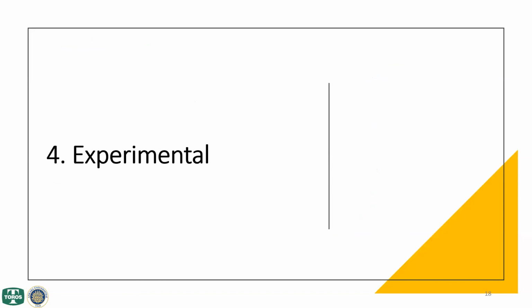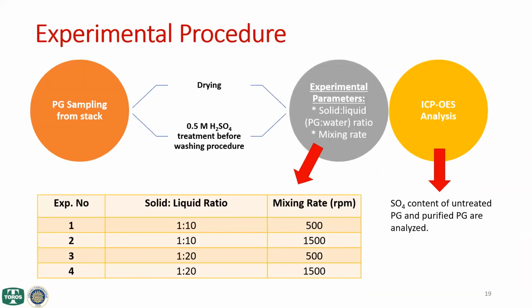Now I will explain the experimental procedure. PG samples were taken from the stack and they were dried. Before the washing procedure, PG was treated with 0.5 molar sulfuric acid. After that, experimental sets with 1:10 and 1:20 solid liquid ratios were prepared and experiments were conducted at different mixing rates. After washing with ultra-pure water, PG samples were filtered, dried, and prepared for inductively coupled plasma optical emission spectroscopy analysis via the wet digestion nitric acid method.